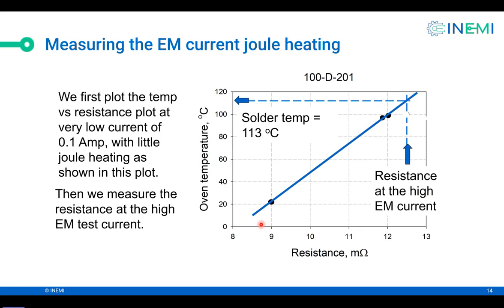So to measure the temperature during electromigration, we first plot a curve. This curve is oven temperature versus resistance, and we measure resistance by using very low current, like 0.1 ampere. So this curve has no Joule heating because we have very low current passing through the specimen. So basically, what this curve tells us is, if we know the resistance, we know the temperature. So then we pump the electromigration current, and we know the resistance of the specimen, and from that we can measure the temperature.